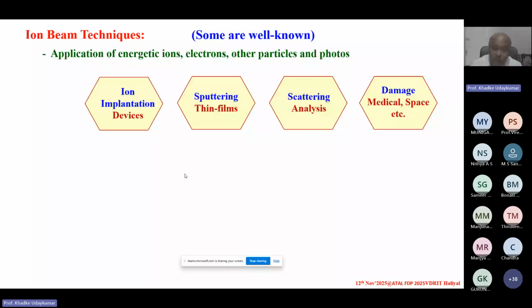But if you take the alpha particle, it is considered to be the heaviest particle compared to the beta particle. Sometimes beta particles are considered to be electrons also, is it not? Whereas alpha particles are considered to be doubly ionized helium atoms. A doubly ionized helium atom is nothing but an ion only. Alpha particles are positively charged particles. If the alpha particles are coming outside from the radioactive source, they can travel a distance of around 4 to 5 centimeters only. Now, if the thickness of the material is very, very large, it only hits the surface. So no chances of penetrating the inner side.